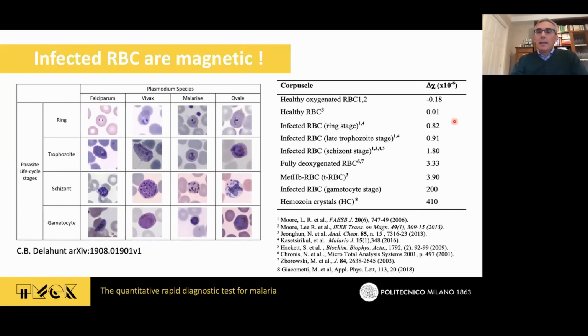But what's the impact in terms of the volume susceptibility for the infected red blood cell? From literature, you can easily find that healthy red blood cells have a difference of susceptibility with respect to the medium which is essentially 0. This means that there is no way to attract them, because the attracting force is proportional to the difference of the susceptibility of the corpuscle with respect to the medium. But what happens when you are dealing with an infected red blood cell in the ring stage? You see that the delta chi is in the order of 0.8 × 10^-6.